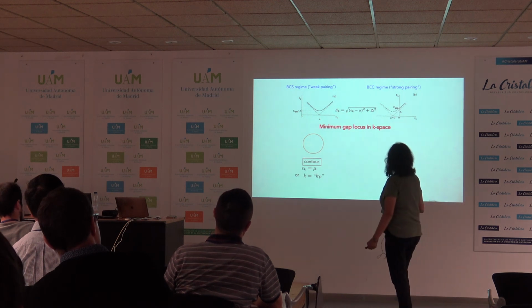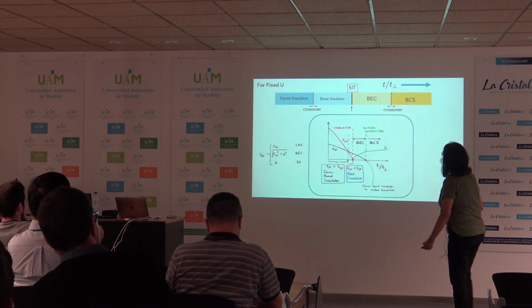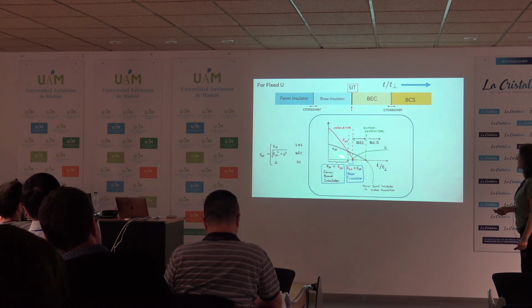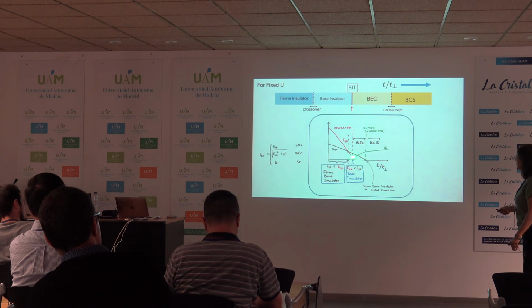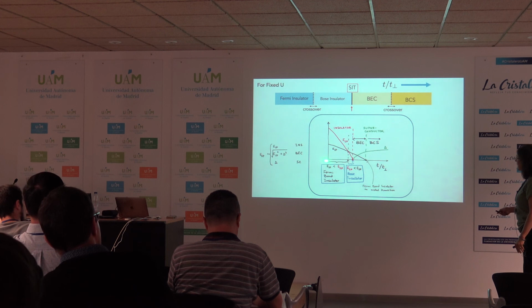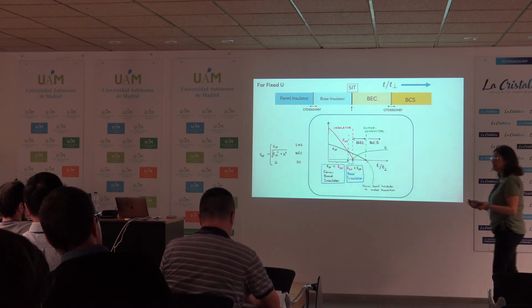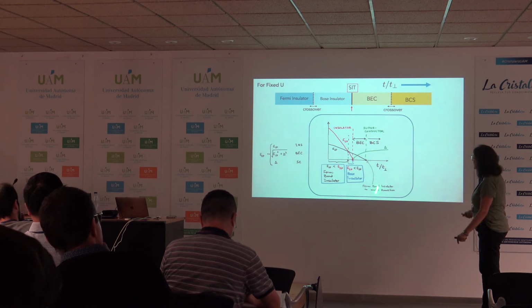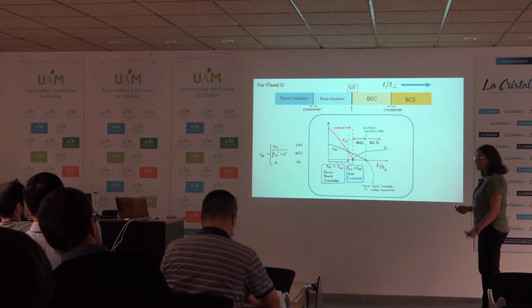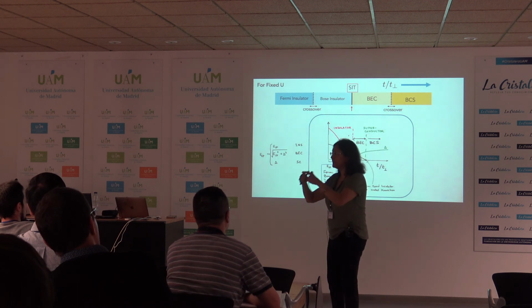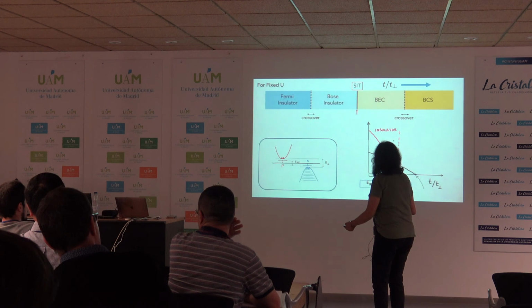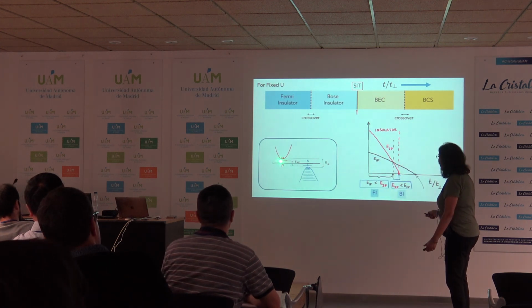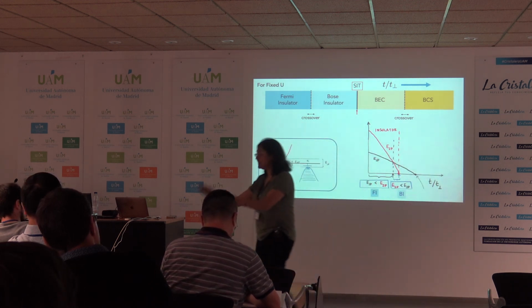Your underlying Fermi surface. Okay, let me just bring this up. So, let's see. If you look at the underlying Fermi surface, right? Up to this value of T, the system is a band insulator, and only after this it is becoming a metal. So even while the underlying bands, the underlying system is insulating, it has already become a superconductor. So this BEC is not being born out of something that already had a Fermi surface. Something like this would be good, that you still have a situation where your band gap, the single particle gap, has not closed. But the two particle excitations are already driving it into a BEC superconductor.